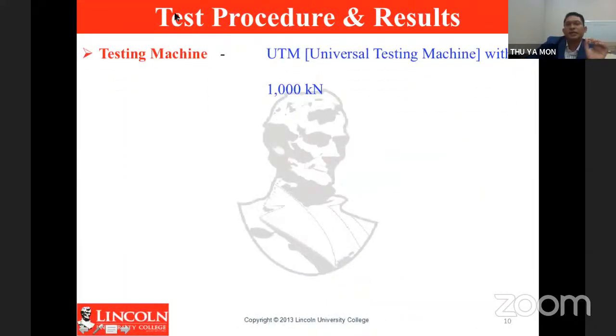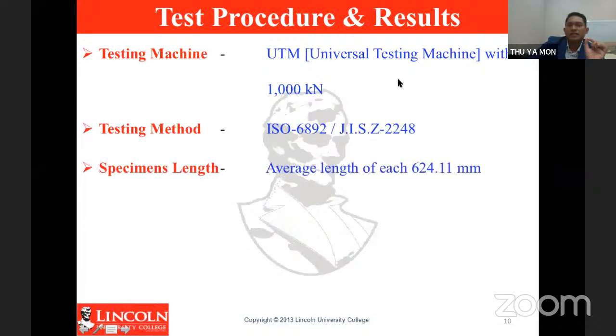So for section 3, the test procedure and research. In my experiments, I used a universal testing machine with a maximum compressive load of 1,000 kilonewtons. The testing procedure and method are according to ISO 6892 and JIS Z2248. For the fabrication of the tested specimens, because of geometric imperfection, the average length of the tested specimens is 624.11 millimeter.